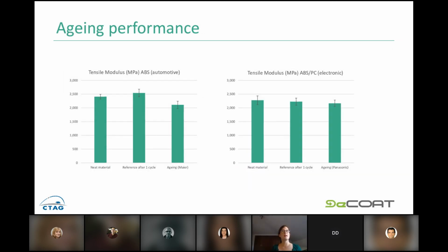We assess also the aging of the virgin material to reproduce this loss of properties due to the years of exposure of the part to different environments. And we see that, of course, there is an impact on the properties due to that. We compare in the graphs the effect of aging compared to the effect of one reprocessing cycle. And you can see that aging is more damaging than the recycle process itself.